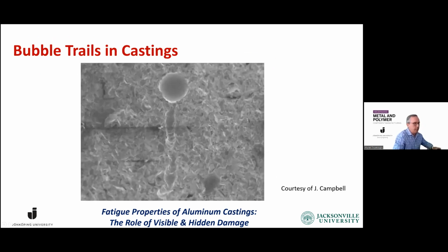And when air is entrained, it of course floats up to the surface, but it reacts with liquid aluminum and leaves a bubble trail. So that's another oxide, that's another entrainment defect. And here you can see the top of the bubble. It's like a balloon, and you can see that it's like a string attached to the balloon that's left behind, the damage left behind by the air bubble. So these melt transfers, this bucket technology, is very, very harmful to our castings.